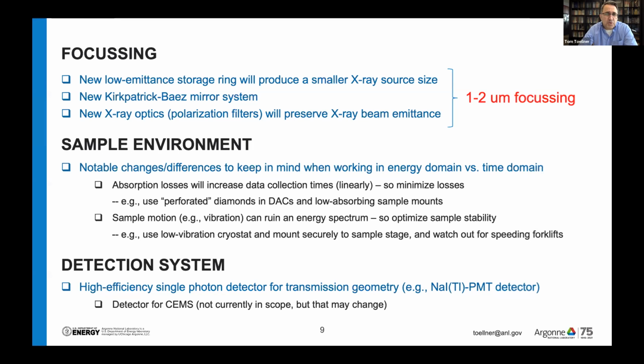So in the case of high pressure measurements using a DAC, one should use diamonds that are milled off on the backside. Sometimes they're called perforated diamonds. And also the sample should be mounted on low absorbing mounts.